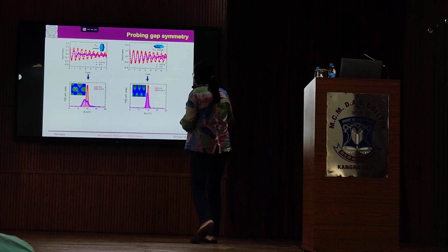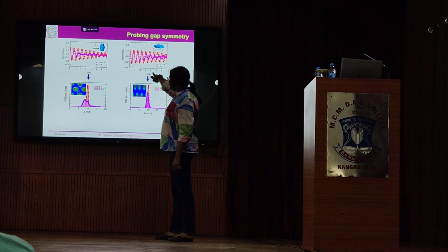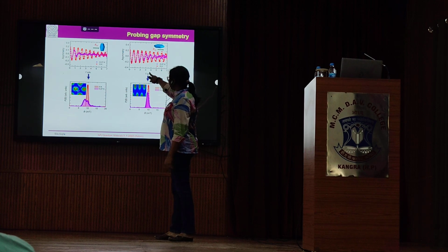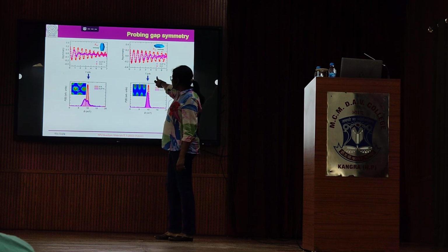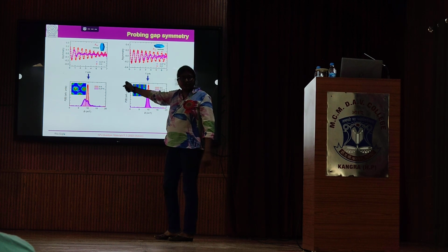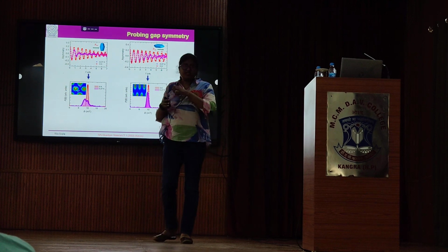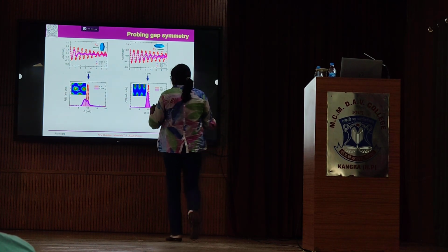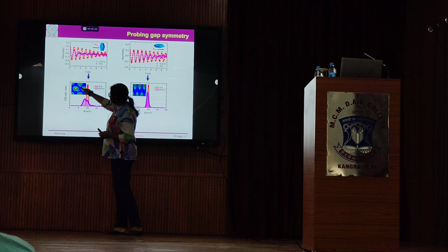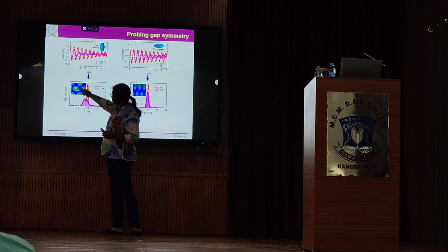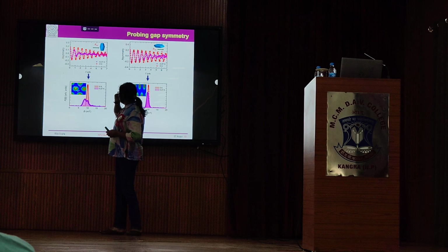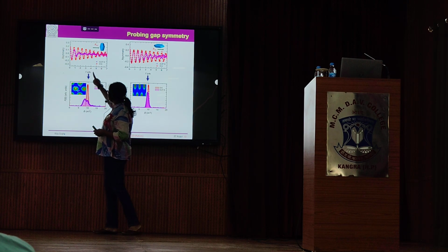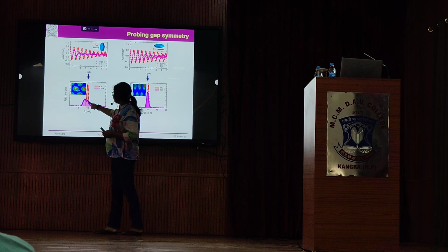Okay, so you can see the first spectra is at 5 Kelvin. There you see the damping is very weak, but as soon as you go inside the superconducting state at 0.27 Kelvin, you have a very strong damping. This is because now the muon is experiencing different fields. So you can see from this picture, I don't know if this is clear to you. Muon can stop between the three vortices, these are the vortices I have shown here in the picture. So muon can in principle stop here, or it can stop in between the two vortices, or it can stop inside the vortices. Okay. So if you take the Fourier spectra of this asymmetry versus time spectra,